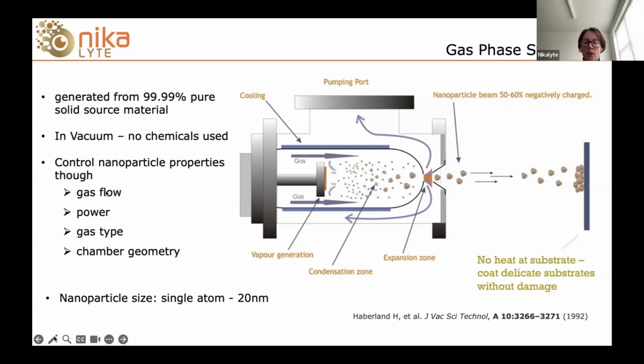We can control the gas flow, so the amount of gas, the amount of argon that we let into that chamber. We can control the power, so the voltage applied to this magnetron. We can then control the gas type. Argon is generally used for generating the vapor, but we can also add other gases. So we can use helium, we can use oxygen or nitrogen if we want to form more complex materials like oxides or nitrides. We can change the distance that the material travels through this chamber.